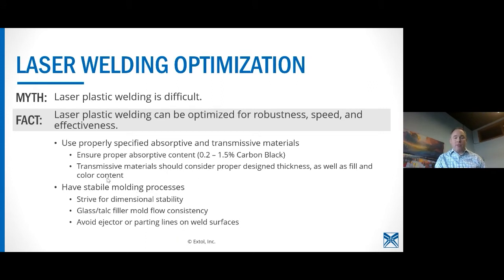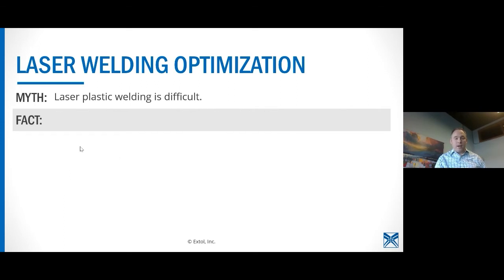Glass and talc filler, but not so much that it exists, but consistency. We've done glass-filled nylons up to 35%, PBTs and the like, really challenging materials up to 2 millimeters or so. And it's not the presence of glass or talc or any kind of filler, but rather the consistency, so that the process can be uniform all the way around the weld room. And then lastly, and this one can be tricky sometimes from a design standpoint, but avoiding ejector pins or parting lines on the weld surfaces is really key to make sure you've got good contact.